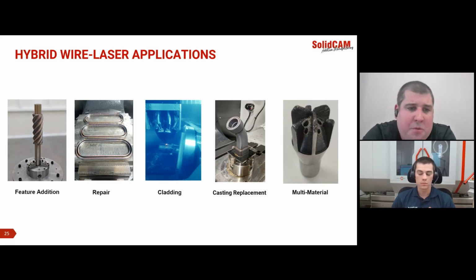Repair work for a hybrid machine is certainly our sweet spot. The biggest thing is that you could establish a surface on a damaged component by machining away that area. So you might have a broken corner or cutting edge on a particular part, machine away that surface, and essentially create your datum surface by using that first machining operation to clear away and normalize the surface that you're about to deposit on, then start printing, and then do your final machining all in one setup. So repair work is one of the big sectors that we focus on.